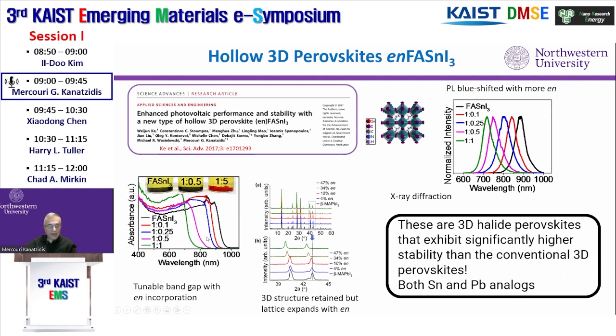However, if you look at the band gaps, the materials actually have different band gaps. And the more ethylene diammonium you use in the synthesis, the wider the band gap. If you look closely, there is some shifting in the diffraction pattern. And also the wider band gap with more ethylene diammonium is indicated by the blue shifting of the photoluminescence. So that was a surprise.